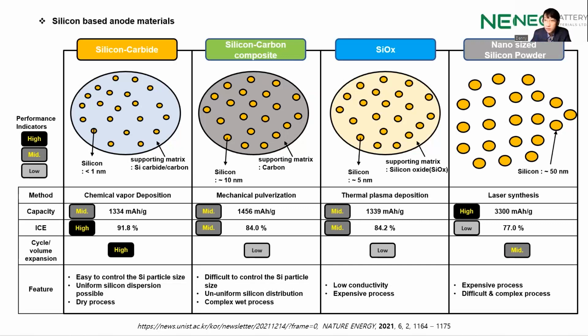These materials have different synthesis or manufacturing methods, energy capacities that determines how long the battery can run, initial coulombic efficiency, volume expansion suppression level, and other various characteristics. And as you can see from the table here, you can just simply think and observe by intuition that these synthesis or manufacturing methods, as I've just mentioned in the presentation, are not only difficult and complicated, but are also highly expensive just by nature itself. And you see these methods: chemical vapor deposition, mechanical pulverization, thermal plasma deposition, requires a lot of energy and time to process and manufacture these silicon anodes.